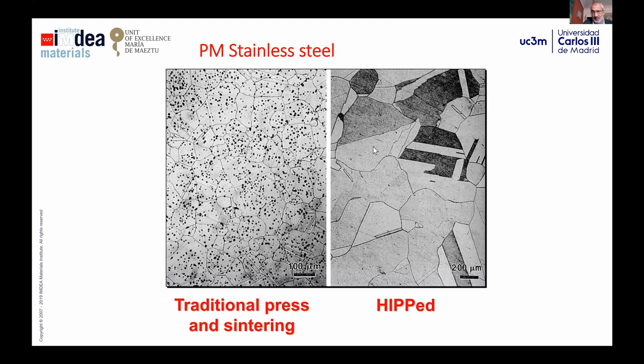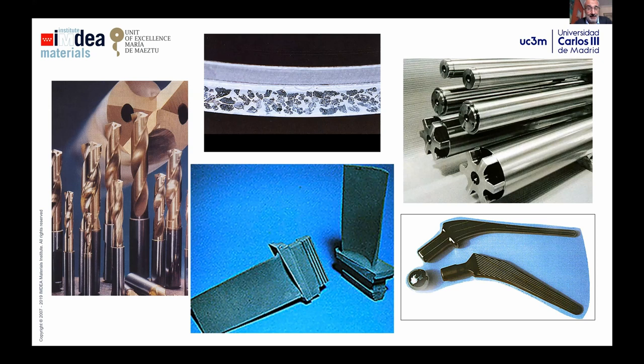You can appreciate the porosity here, but due to the fact that you need such a long time to reach this microstructure, usually the grain grows more than you desire. So anyway, in that case, hot isostatic pressing has been used for many, many years to produce, for instance, high-speed steels, as you have here, these ingots of high-speed steels, with the best properties that you can reach in any other possibility or alternative method.